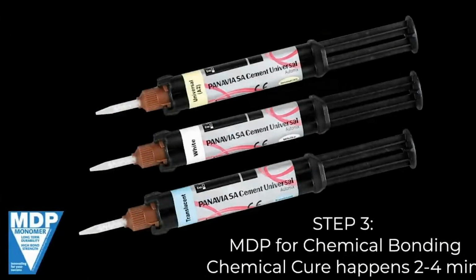So I'm using the Panavia SA Universal Cement, and it's important to note the reason it's bonding is because Kuraray has placed their MDP, which is the ingredient necessary to bond zirconia, in the actual cement. So the MDP for chemical bonding is in the Panavia Universal Cement, and you'll have a chemical cure that happens between 2 to 4 minutes. So you don't need an additional primer because the MDP is in the cement.